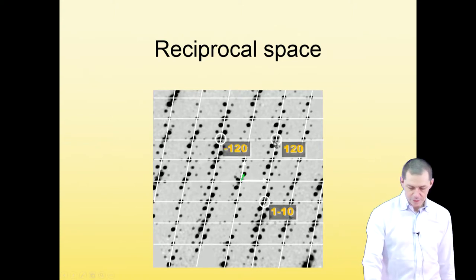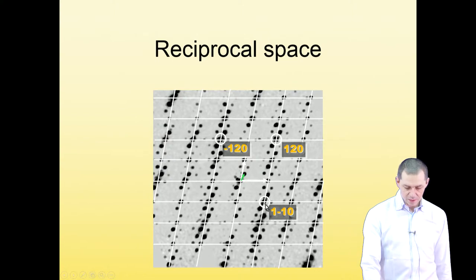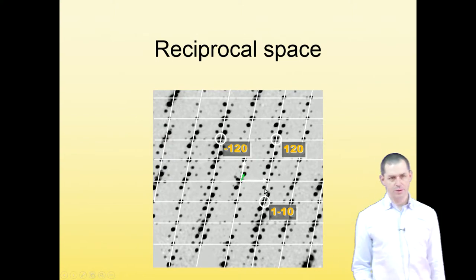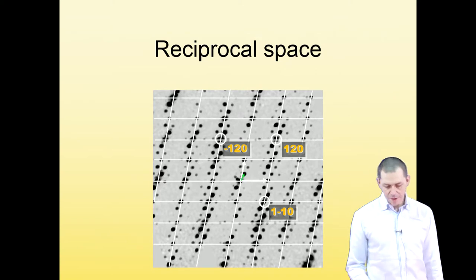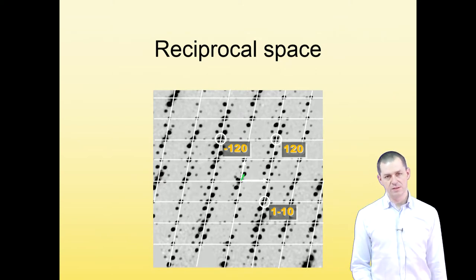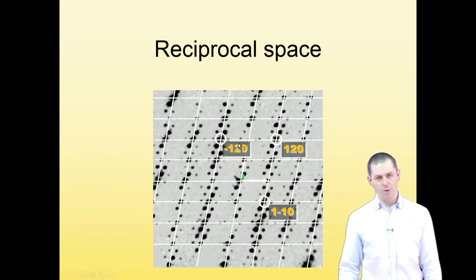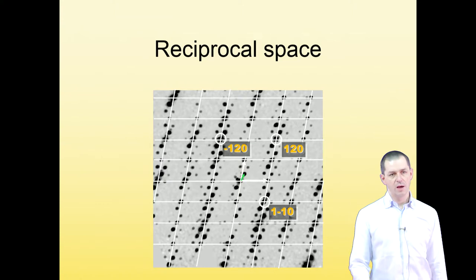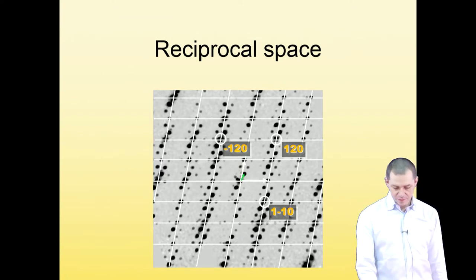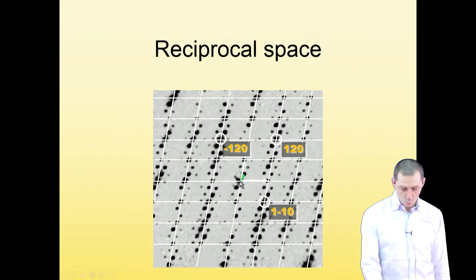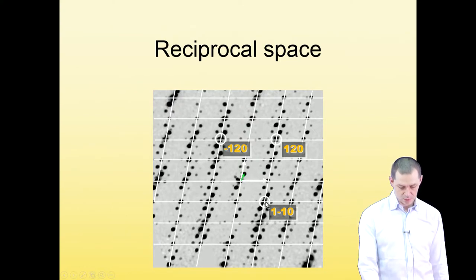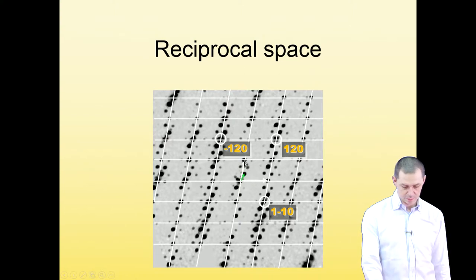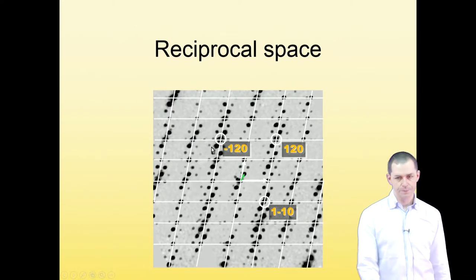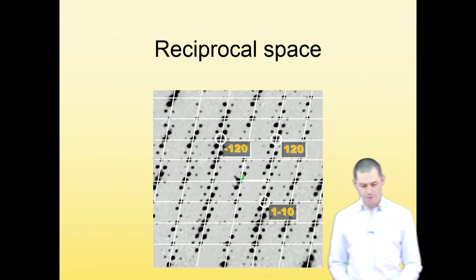And the reflections, so the spots that are on the corners of the average reciprocal lattice, can be described with three indices. The third index is always zero here because we are in the plane of L equals zero. But this index, for example, is obtained as 1 times A star minus 1 times B star. So this would be A, this would be B. So it's 1, minus 1. This is 1, 2. This is then minus 1, 2. Simple, normal, standard indexing of reciprocal lattice.